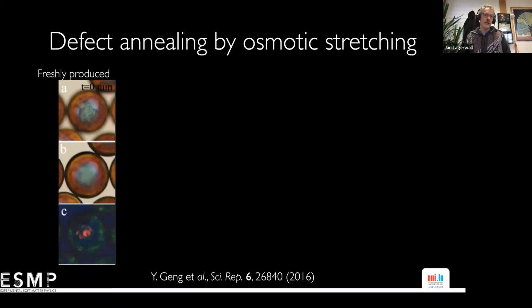Okay, so we make these shells with the cholesteric liquid crystal phase, making out this part. And when they are freshly prepared, they look something like this. So this is in transmission microscopy without polarizer. And you can see it's pretty messy. There are lots of defects. And here you see the reflection. You see some color, but it's really not at all very regular and not good control. And that's because, yes, we can make the shell, but this helical structure takes some time for it to organize in the way we want it.